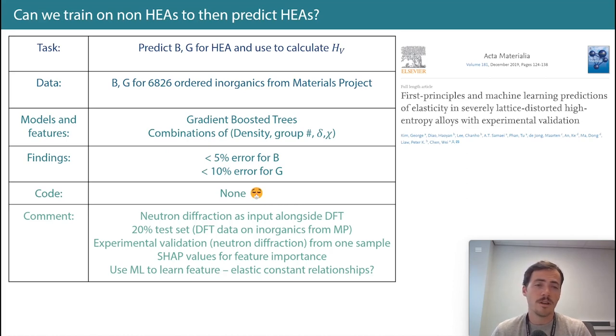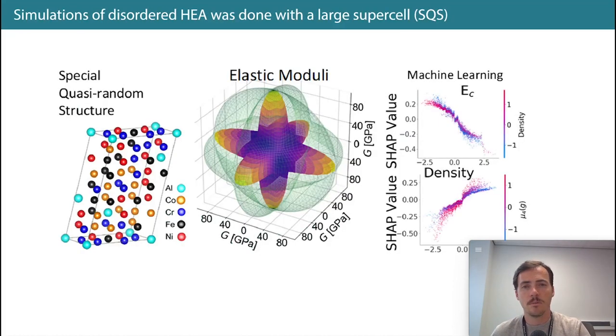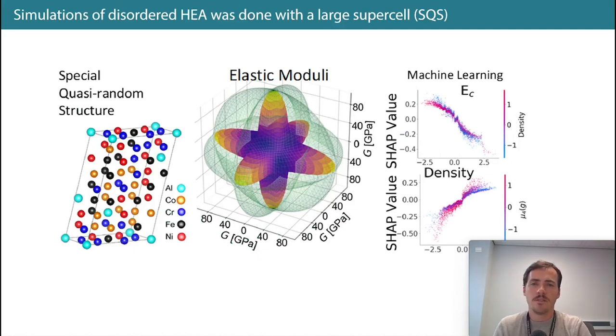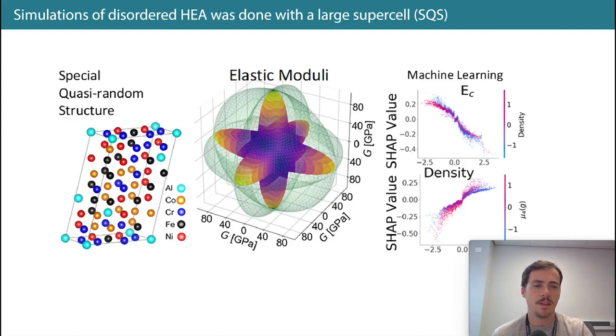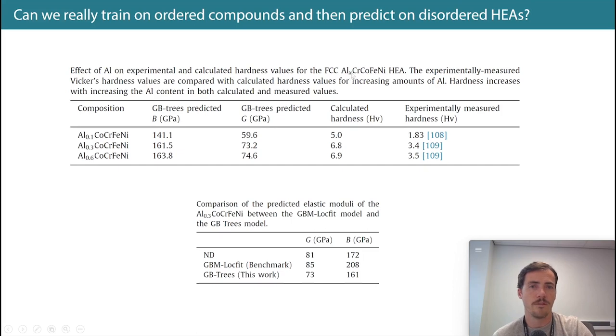What would be really interesting is saying: okay, if you build this model on ordered inorganic compounds, does it work to predict HEAs? That would have been worth validating carefully. But their analysis leaves something to be desired. They made predictions for one experimental HEA family — an AlCrCoFeNi system with varying aluminum content — and experimentally measured its hardness, using their ML-predicted moduli with an empirical relation to calculate predicted hardness.